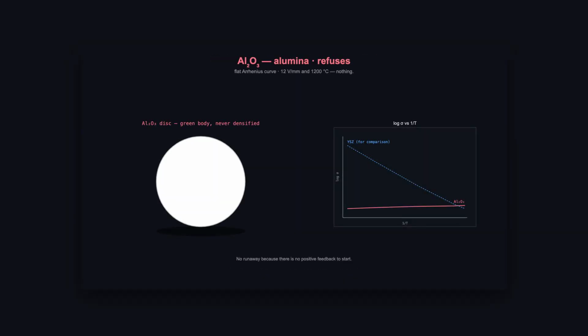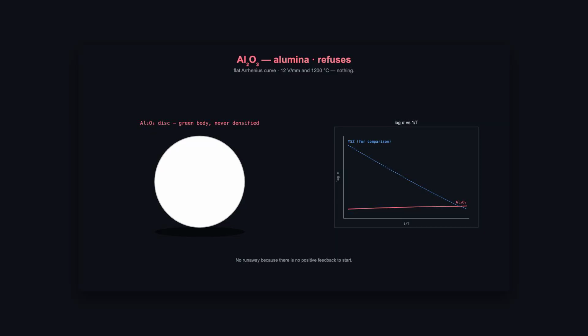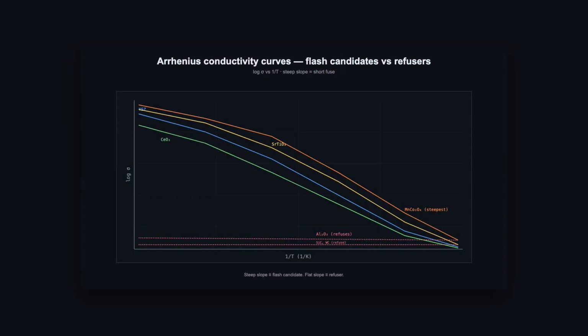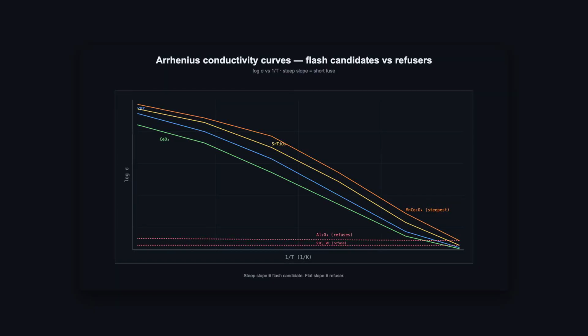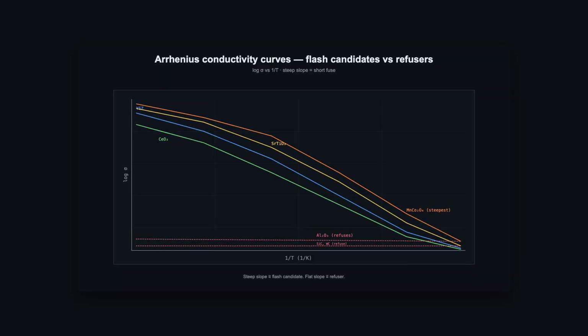Pure alumina, on the other hand, refuses. Flat Arrhenius curve, no runaway, no flash. You can push it to 1200 Celsius and 12 volts per millimeter and watch nothing happen. Tungsten carbide, silicon carbide, most pure oxides outside the conducting families. They all refuse. The pattern is simple. If your conductivity versus temperature curve is steep, you can flash. If it is flat, you cannot. Salvatore Grasso at Queen Mary in London has spent a decade cataloguing these curves and predicting which oxides will flash next. Unless you cheat.